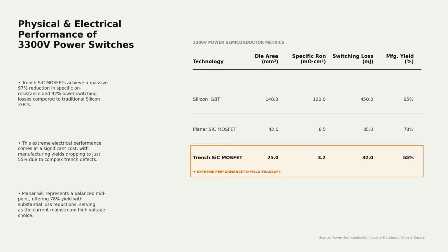Transition to trench silicon carbide architectures represents a major electrical performance leap offset by manufacturing complexity. Trench devices achieve a specific on-resistance of 3.2 milliohms square centimeter. This is a 62% reduction compared to planar silicon carbide and a 97% reduction compared to legacy silicon. This architecture enables a highly compact die size of 25 square millimeters. This physical compaction theoretically increases the gross number of dies per wafer by 68% over planar designs.